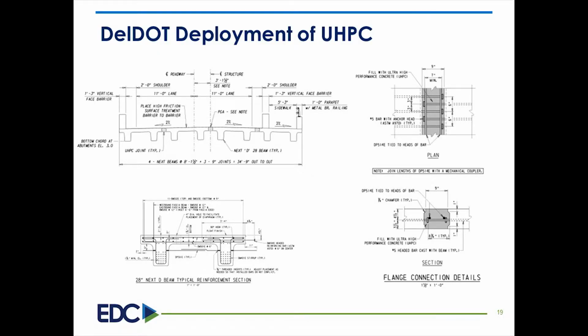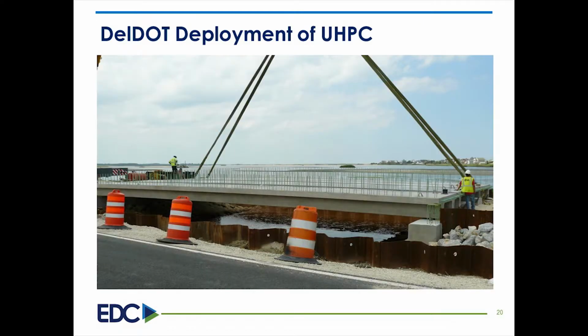This is what the details look like. These are the next beams, very similar to the one that we did not use the UHPC on. And you can see very similar details though. Just lay them out. You got a total of 4 beams that get put in there, and then you just fill it with UHPC. This one, I had a contractor who was very good. Listened to the supplier all along, had absolutely no issues with it.